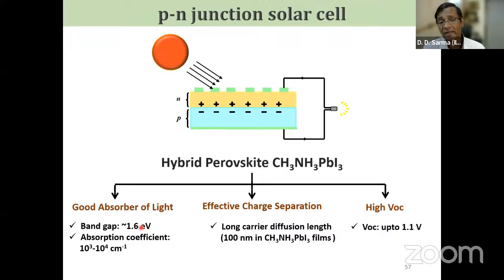Silicon has an indirect band gap, which is a very poor absorber of light. This material has a fantastic absorption coefficient. That's why you can make it so thin. It has very long carrier diffusion length, and it can give you open circuit voltage up to 1.1 volts, which is very large. So everything looks to be good.